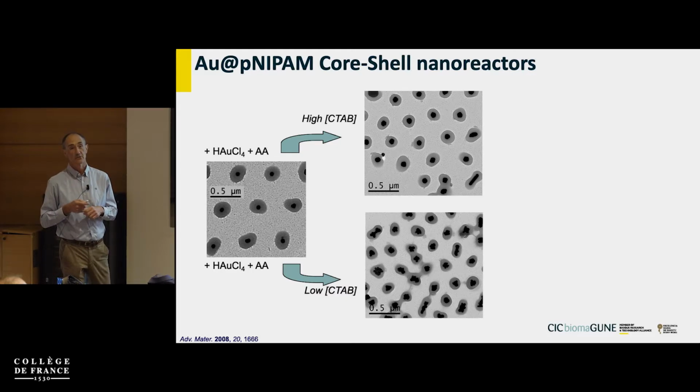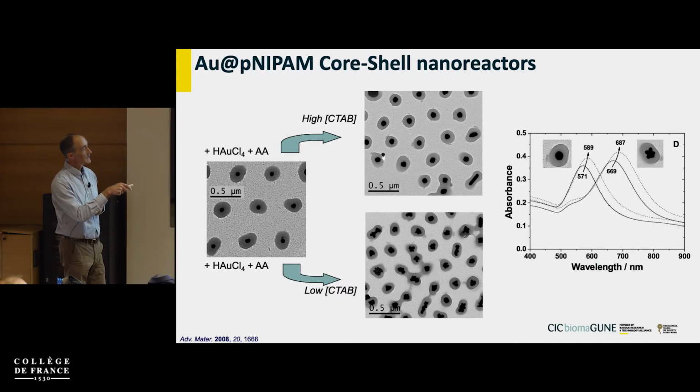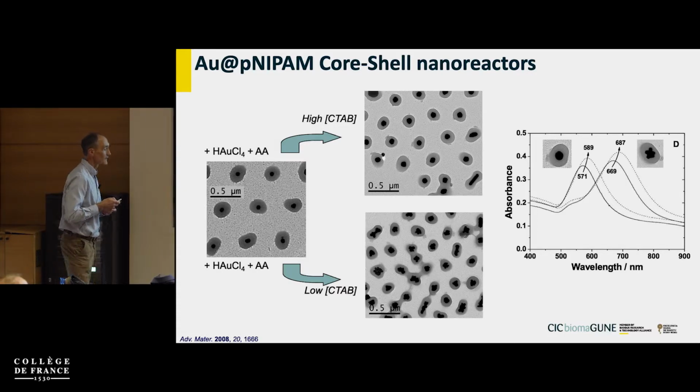So they become sort of star shape, and that you can also see by a clear shift in the position of the plasmon resonance. And then both of them would redshift when you change temperature, but to a different degree. So these ones also become a bit more sensitive to changes in the refractive index, which is in agreement with the theory that I explained in the first lecture.